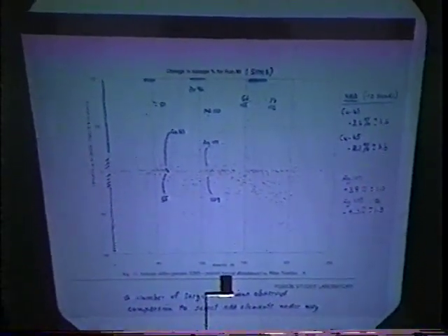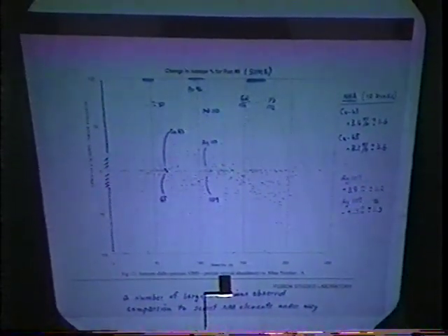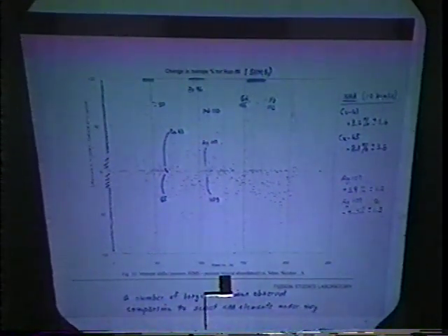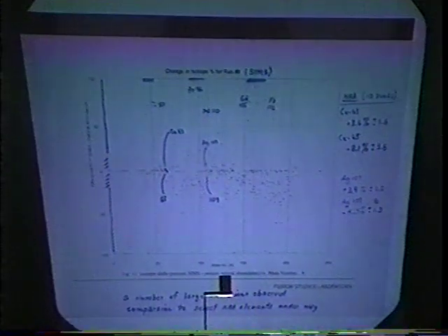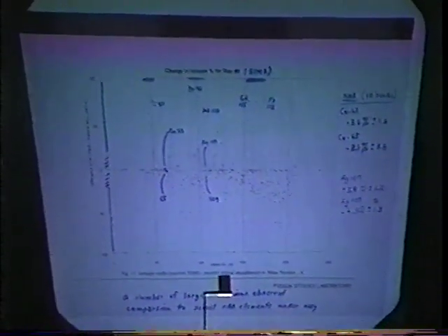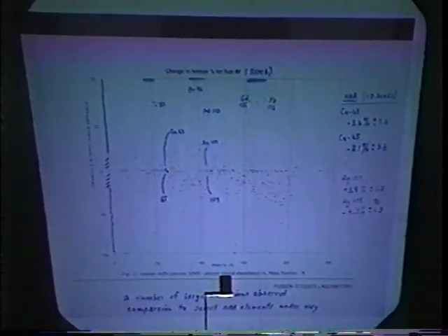And so we've done this with neutron activation analysis, using 10 beads to get an average. It gives much higher percent, same direction, plus 3.6% for copper 63 and minus for copper 65, with fairly large uncertainties. There's an overlap. You should have plus and minus equal, but when you do it this way, you get somewhat larger uncertainties and not exactly the same number.